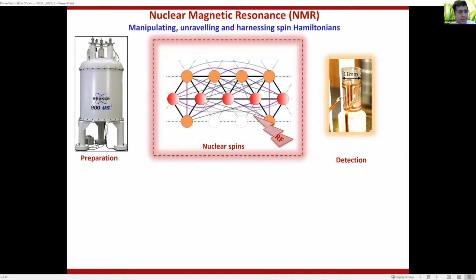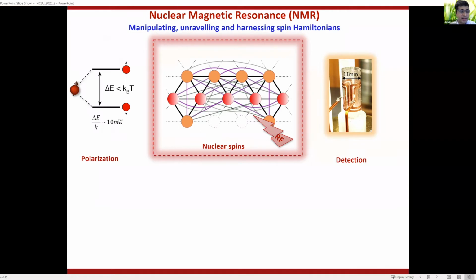So typically, you put spins in a magnet, and these spins are like little magnets themselves, and they align in the direction of the magnetic field. Equivalently, you open the energy gap between spin down and spin up that's proportional to the magnetic field, and you get a population imbalance between the two states. And this is what you measure with NMR.